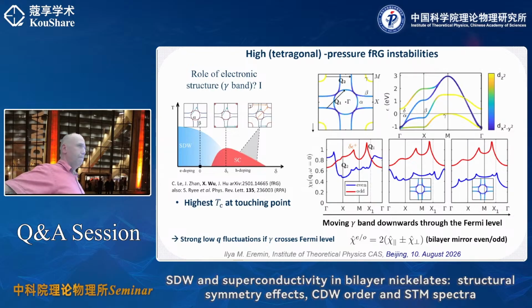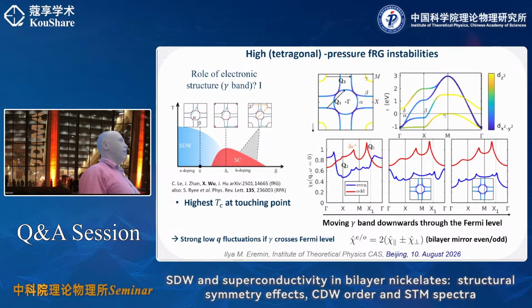There's some debate on the different roles of the two orbitals in the superconductivity. Right. Here it's dz squared. So essentially, okay, I would say that even from a strong coupling perspective, it's not that different, because in strong coupling, they say the z squared is localized. However, without the z squared, you don't get superconductivity, because x squared minus y squared is just quarter filled. So there, z squared provides a medium. Here in the itinerant picture, it plays a very important role because this is where the gap is also the largest. But still, z squared is mostly correlated. So the only difference is whether z squared is a medium or z squared is a player, right? But in both cases, z squared plays an important role.